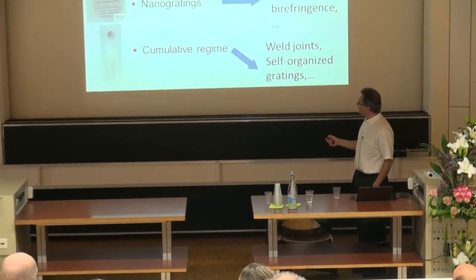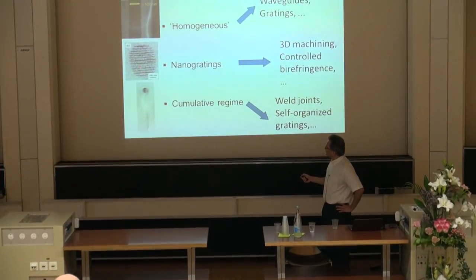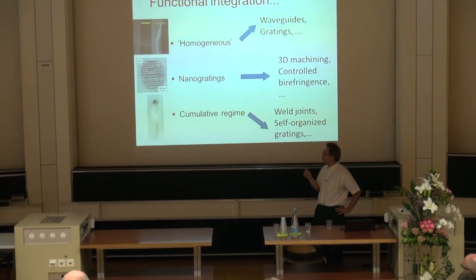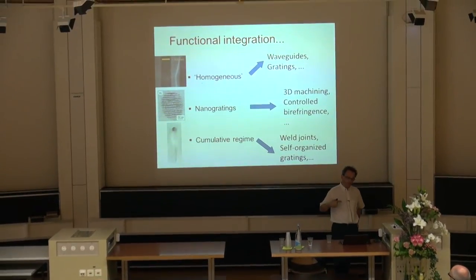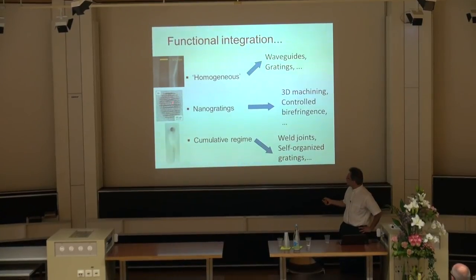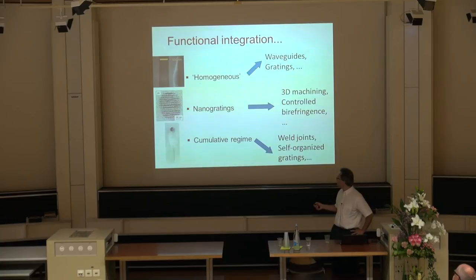Now, these fascinating things, and I'd like to say a few more words about that, this nanograting. You see, this is the size of the laser beam when it's focused. So you see, within the focus, you have the self-organized structure. And that's some of the smallest things ever made with a laser. So it's beating the diffraction limit. Of course, it's smaller, a few tens of nanometers. And this is self-organized within the electrical field of the laser. This has a lot of interesting properties, not only for etching, but also for optical properties, because here you have, in a way, modulations of the refractive index. So that's useful if you want to have some controlled birefringence. Now, if I dump a lot of pulses very fast, I get into a regime where I melt the glass, and that's of interest, for instance, if you try to weld glass together.